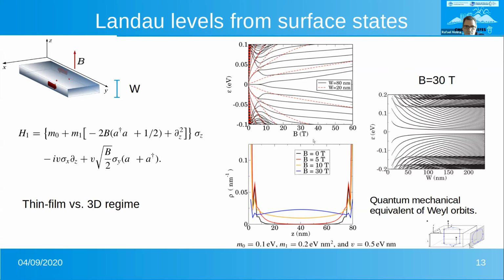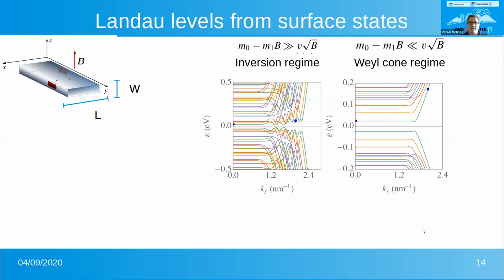At this particular value of the magnetic field, the surface and the bulk states start to hybridize. Here I show the wave functions, and for example, for 30 Teslas, you see a mix of bulk states and surface states in the density, and this will be the quantum mechanical equivalent of Weyl orbits. And now, in fact, what we find is that there are two parametric regimes, depending on the parameters of the Hamiltonian. We call them the inversion regime and the Weyl cone regime.